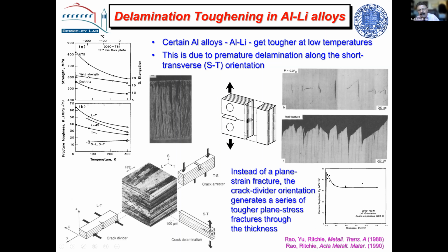And I've shown it here. And this is the orientation where these alloys really look the best. This is the LT orientation where you get the maximum toughness at liquid helium temperatures. And what happens is it delaminates along these planes when the crack tends to break, and it's delaminating perpendicular to the crack path. But what that does is it separates the material from a plane strain fracture into a series of plane stress fractures. Because at low temperatures, these planes get weaker and it tends to delaminate.